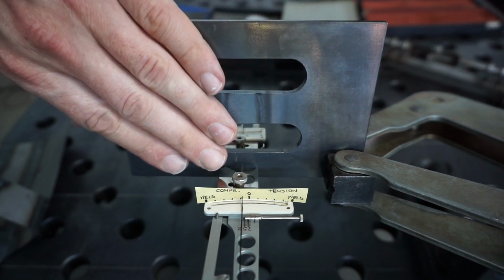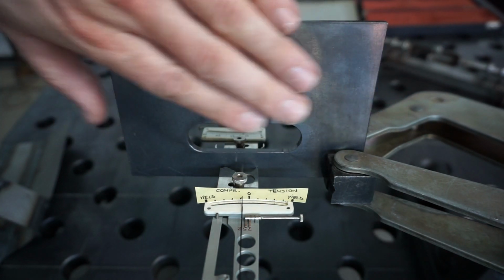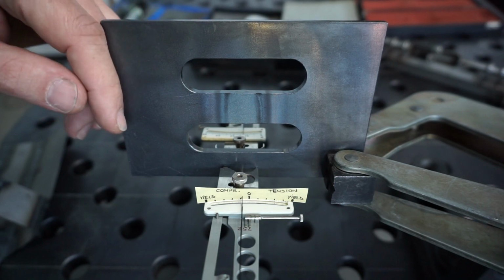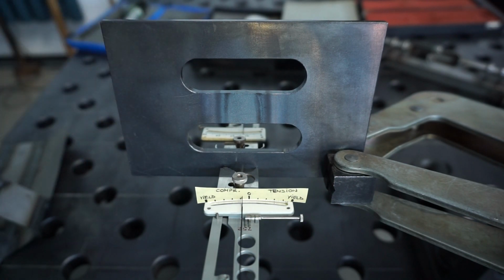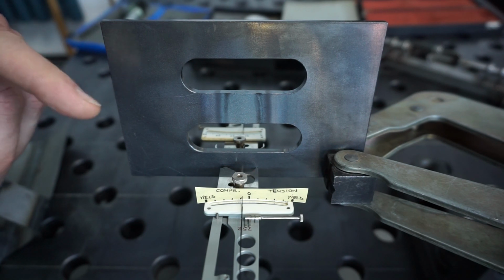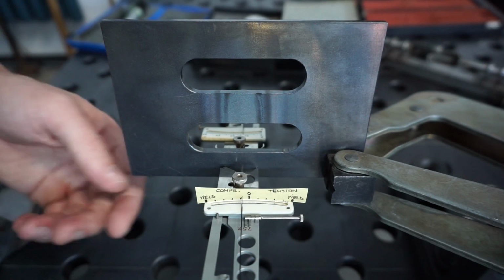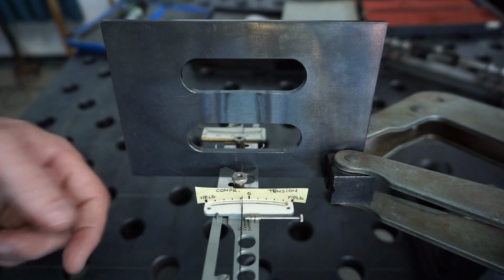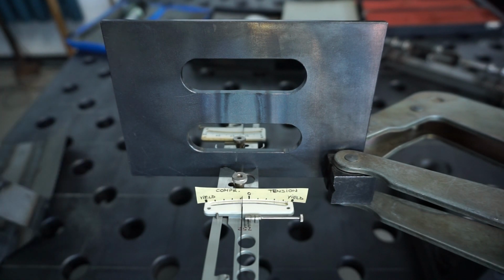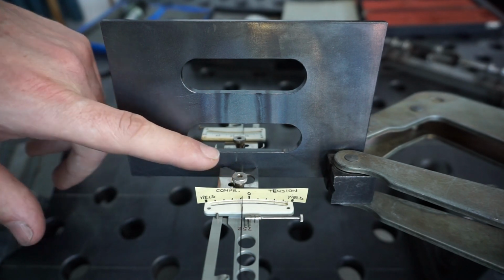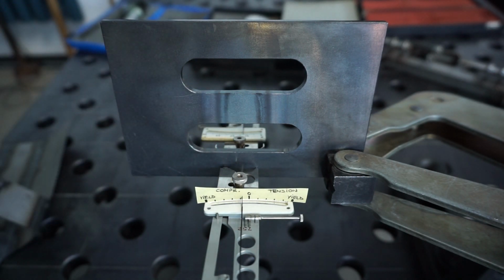Well, the 3-bar truss has now almost entirely cooled. But interestingly, and that's important to note, our strain gauge indication is not back at 0 where we started from. So if we can trust the strain gauge, the outer bars now experience residual compression stress of almost 20% of the material's yield strength. This in turn means, times -2, that the central bar now experiences almost 40% of the material's yield strength in tension. That's quite a lot, isn't it?